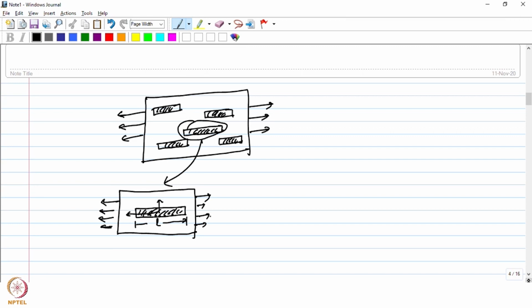So as I said before, the fiber will be subjected to a normal stress, and as the load is transferred to the fibers through the interface, there will be a shear stress developed along the interface. So if we neglect the strain hardening, then the shear stress on the fiber surface will not exceed the yield stress tau naught. So if you take an equilibrium of forces between the stress in the fiber and the shear stress acting on a length L by 2, then this is what you will get. And we are considering half length of the fiber because it is loaded from both the sides.